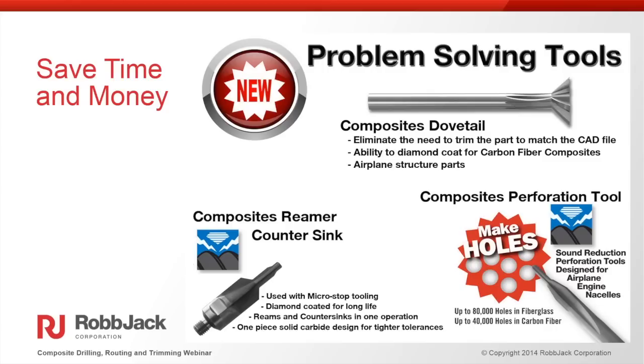But by coming up with a dovetail tool that can not only put the dovetail but trim the part in one application, and because we make it out of a solid carbide blank, we have the ability to diamond coat it. You get the really long tool life, and we've eliminated operations. So by coming up with a combination tool or a tool that solves a problem, you can save millions of dollars over the production of the part. And in this case, that's what we've done. We've saved numerous hours per part and saved the customer a considerable amount of money.